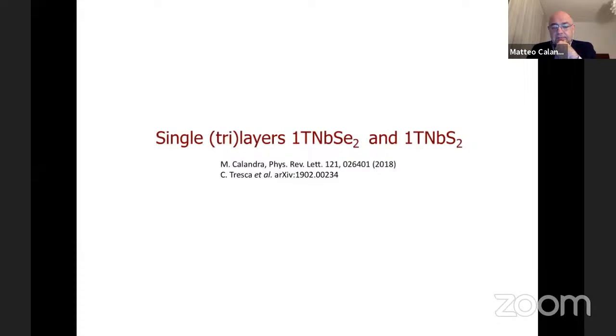I see. But for instance, since you're not including electron-electron correlations, I would say that you have an electron system and electron-phonon coupling, right? No, we also have the electron-electron interaction, because we have the exchange and correlation functional. When we use a semi-local functional, we have what is called the local density approximation and so on. But when we use a more complicated approximation to the electron-electron problem, like HSE06 and so on, you also have Hartree-Fock screened exchange. So you have electron-electron interaction, mostly the Hartree-Fock term, and only locally the correlation part. But you have the electron-electron interaction.